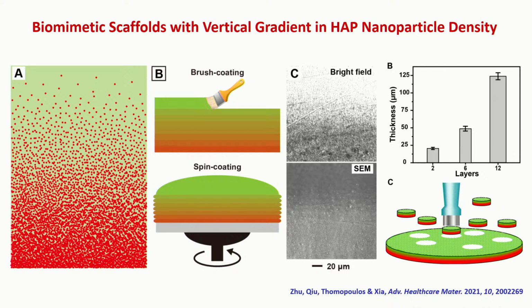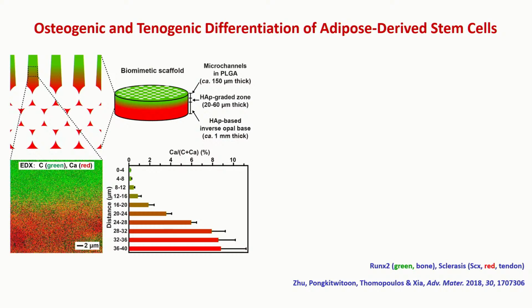Okay, this is 2 layers of coating. This is 6 layers. So every layer is going to give you about 10 micrometers of coating, either using brush coating or spin coating. And when we do spin coating in particular, there's another advantage. You can spin coat on a pretty large wafer, and then you can punch them into small discs. Each one of them could be used for one repair. So with this kind of parallel fabrication, you can generate identical scaffolds in just one fabrication. This could be like 30 or 20 almost identical scaffolds for next step applications.